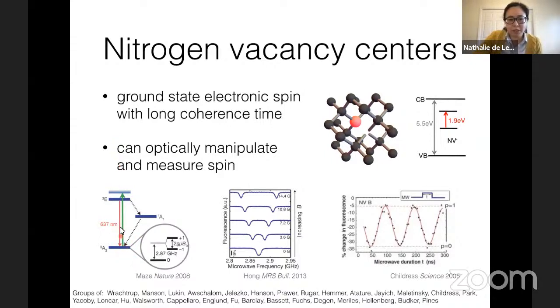Basically, if I just shine a laser that is about as sophisticated as a green laser pointer at the NV, and I look at how many photons I get back, then if I start in ms equals 0, I can cycle a bunch of photons and get a high fluorescence rate. But if I start in one of the other two spin sublevels, I have a rapid intersystem crossing to a dark state, and that suppresses my fluorescence a little bit. So this is optically detected magnetic resonance, and I can see this magnetic resonance just by measuring fluorescence. You can use this, for example, to measure the local magnetic field, because you can see Zeeman splitting between these different sublevels.